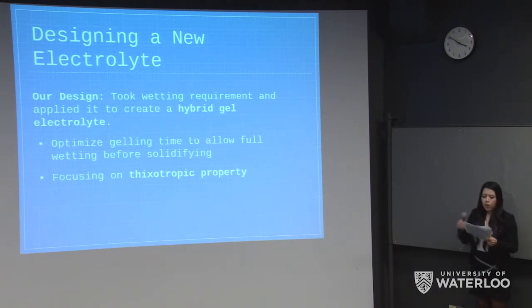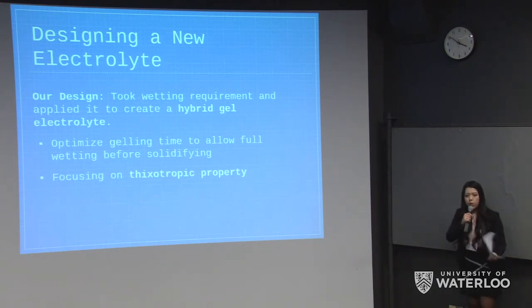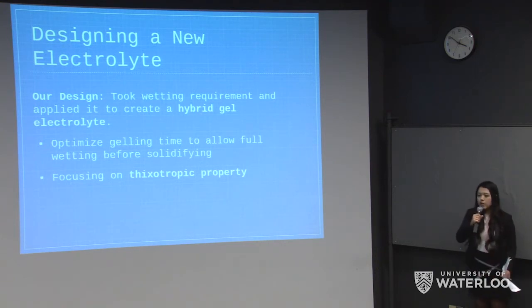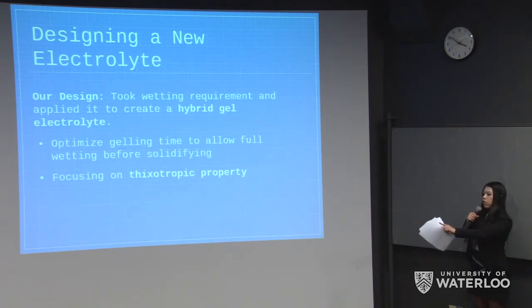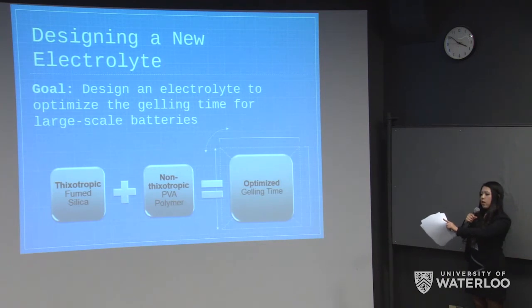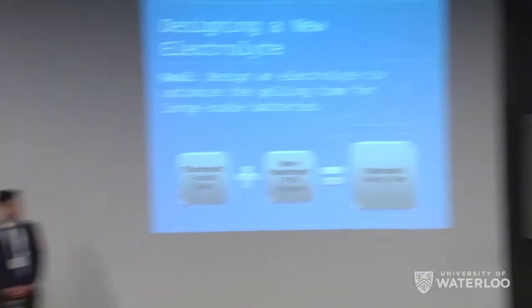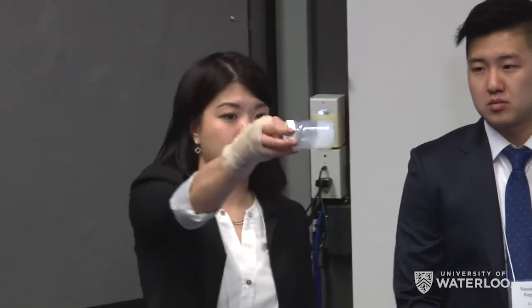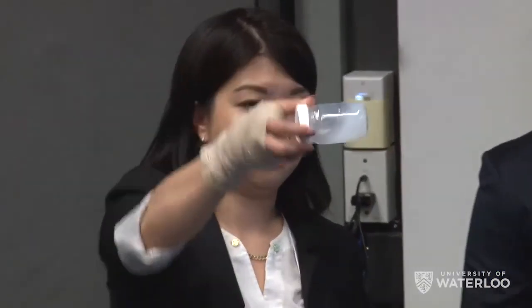So when a gel is thixotropic, it means that when it's left by itself and it's left sitting, it is gel-like in nature. But once you apply a shear stress to it, so if you shake it or agitate it, then it becomes fluid-like and it can move freely. So if Jessica can just show, the clear one that she's holding is just a pure liquid electrolyte, and you can see as she's moving it, it moves freely within the container. And a thixotropic solution, that one has 5% fumed silica. You can see that it's a lot more viscous.